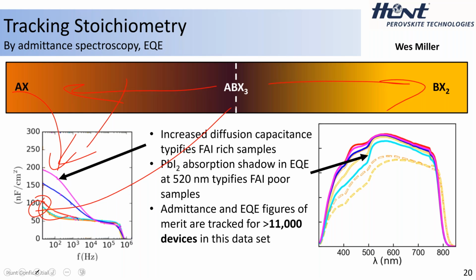Further, if you swing to the other side, we have the opposite issue. Now we have excess BX2, in this case lead iodide. Lead iodide is also a semiconductor. It's a wide bandgap semiconductor, around 2 eV-ish, something like that. See here in our spectral response to the right, that is the red edge, or the low energy edge, of the spectral response of the lead iodide, producing what we call internally the lead iodide shadow. So if you have too much lead iodide in your system, you actually see a reduction in the spectral response at less than 500 nanometers. So we have two really great key indicators from our other battery of tests that give us a strong indication of what the stoichiometry of the surface of our material is.